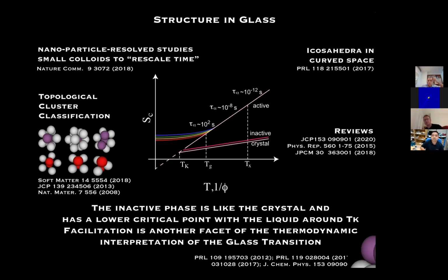So they do, I mean, when the structure's less obvious. In 3D, one could take very polydispersed hard spheres, say, but they tend not to crystallize, as you know. But perhaps a more pure way to answer the question is that in high dimension, where it's actually all solved, there is no local structure. In high dimension, everything is 2-point correlation functions, and there is a complete glass transition. So what you say is completely valid in high dimension. There are no local structures in high dimension. They just don't exist in any meaningful way.